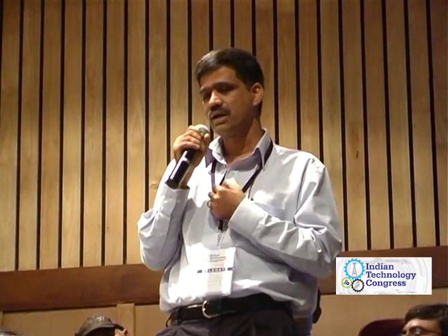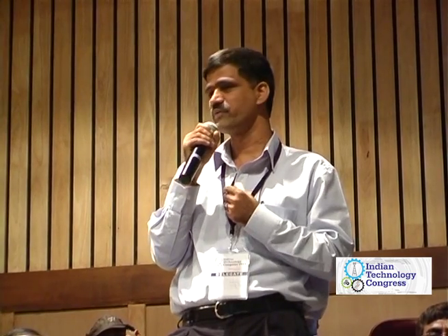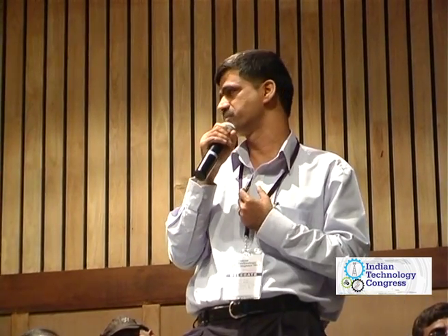So the recent advancement is trying unconventional machining. People are trying EDM, LBM and abrasive water jet cutting. In fact, I worked on abrasive water jet cutting of MMCs at IIT Madras, and I know the major problem with abrasive water jet cutting is the deflection of the jet. The jet will not deflect in the top region, which is called the cutting wear mode, and in the bottom we call it the deformation wear mode, where the jet deflects more and the surface finish is reduced.